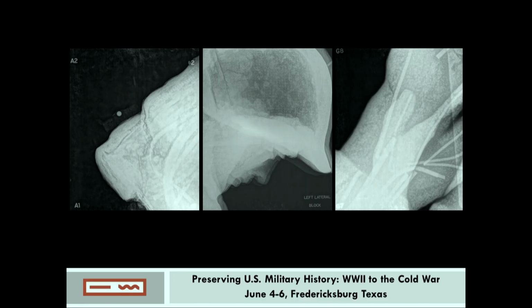The X-ray was not an easy undertaking owing to the thickness of the sculpture and its geometry. The results indicated that the sculpture was suffering from advanced deterioration, and this agreed with our own detailed visual inspection. Severe cracking of the concrete was clearly related to the corrosion of the internal steel armature and continuous infiltration of water, made worse by the application of the impermeable coatings, which prevented the escape of moisture from the saturated concrete.